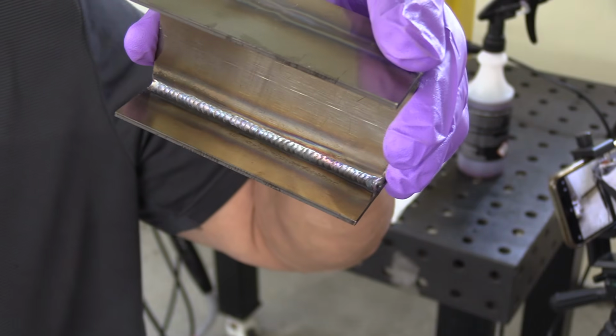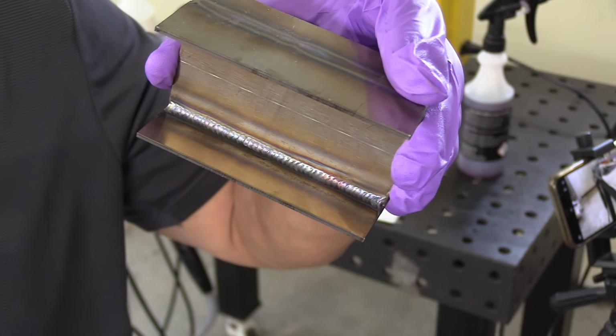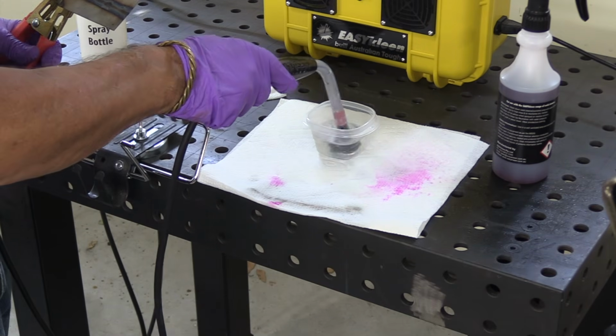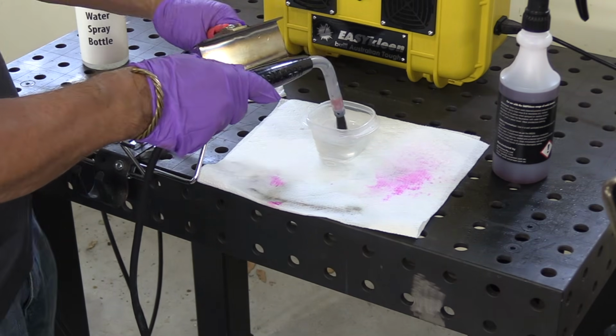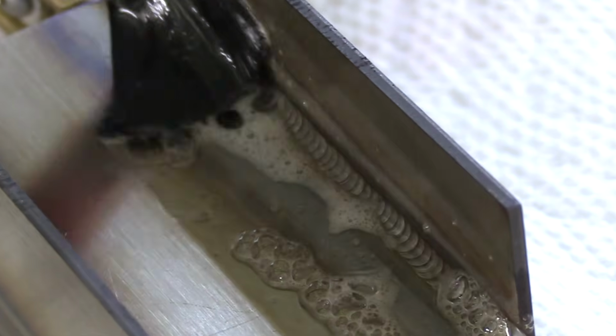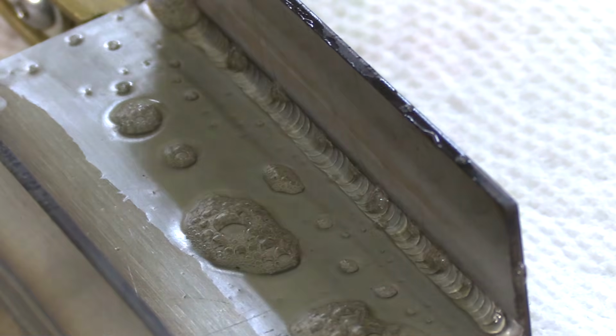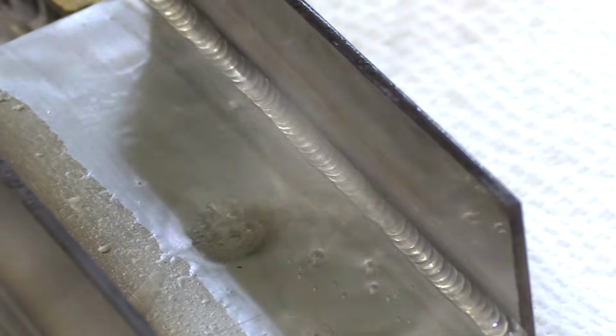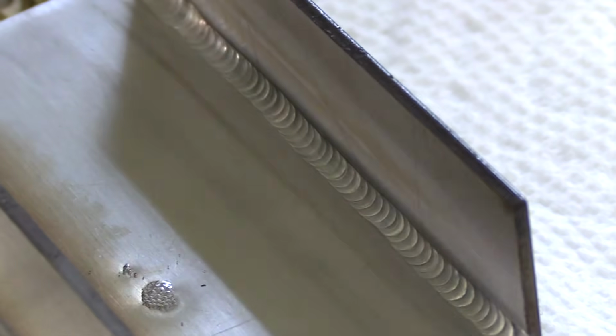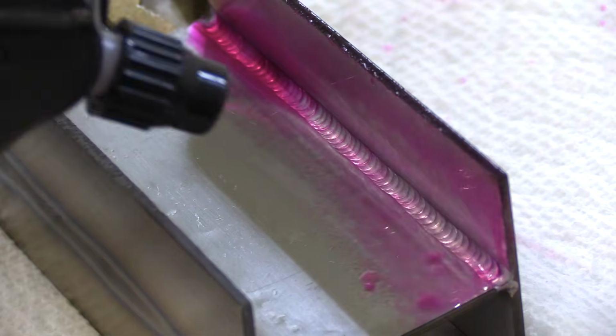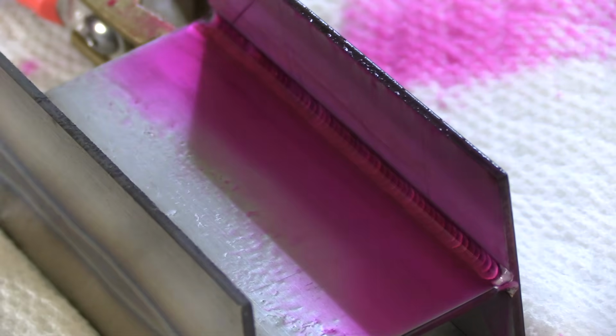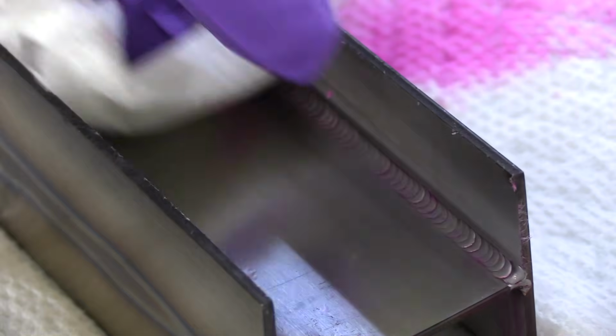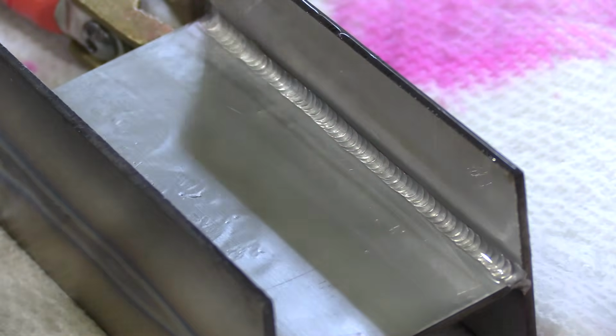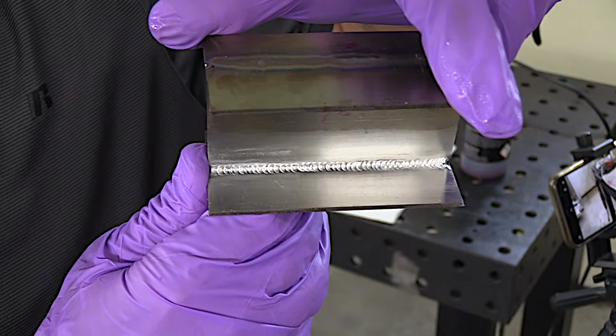So let's take that T-joint that you saw earlier. It's got some good discoloration on there, and let's see if we can remove that using this machine. Now it uses a cleaning solution, which is a mixture of phosphoric and citric acid. You wet the brush with the piece grounded and it removes a layer of material. Then you neutralize it, let that set a minute, wipe it off, rinse it off. Let's take a look at that.